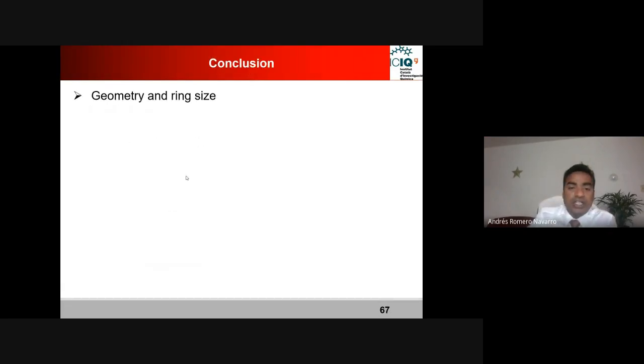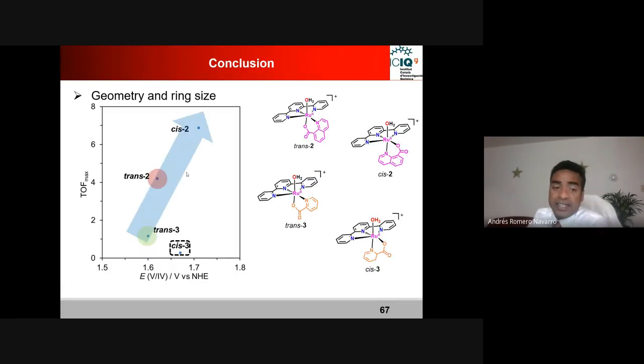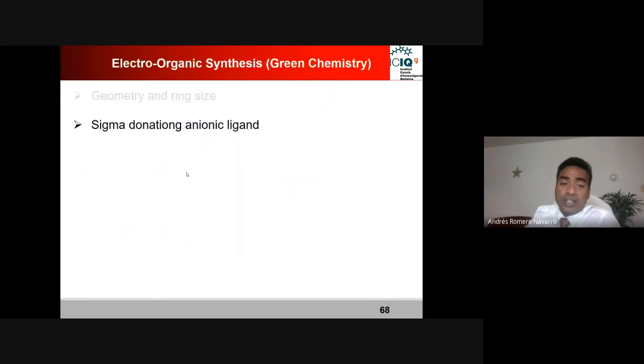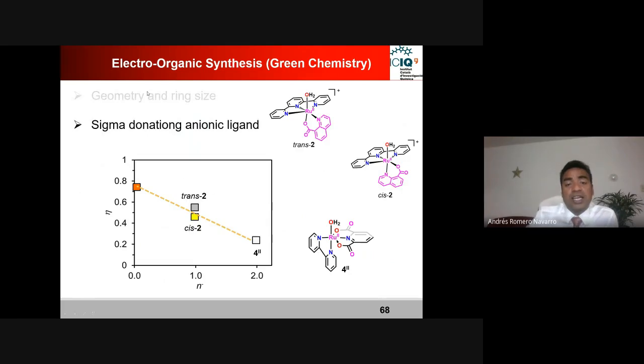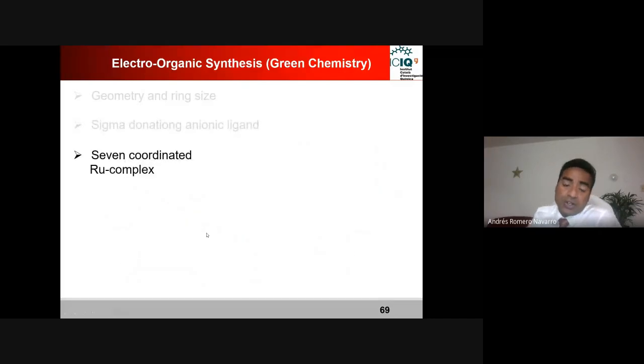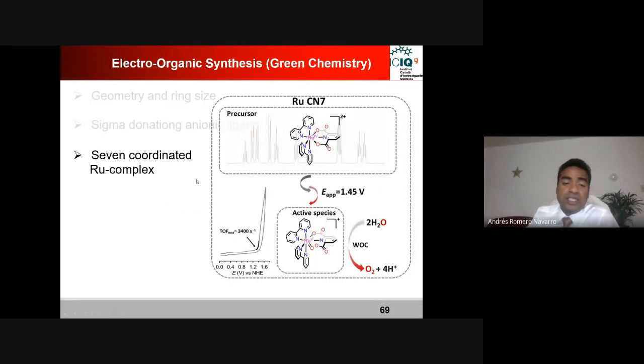Now I move to the conclusion. I showed you that geometry and ring size can have a dramatic effect on the turnover frequency, that is, the activity of the small catalyst. I showed that introducing a sigma-donating anionic ligand can help reduce the overpotential of the system. And then I showed another example where you can form this seven-coordinated compound, this pentagonal bipyramidal geometry, which ultimately can generate an active catalyst with very high turnover frequency.